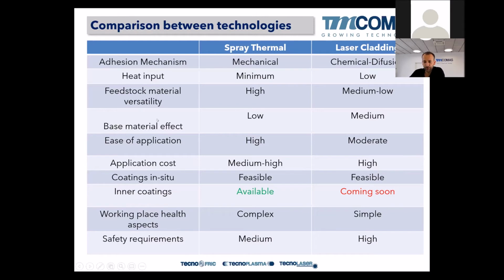Base material effects. So yes, in thermal spray it is low. There is no welding, so the weldability is not important for us in thermal spray. So the effect of the different material in the base material is not important in thermal spray. We can spray over copper, over aluminium, over titanium, steel, stainless steel, Inconel, Hastelloy, whatever, no? While in laser cladding, the weldability is very important because we have to perform a weld, and it is mandatory to have a look at it.